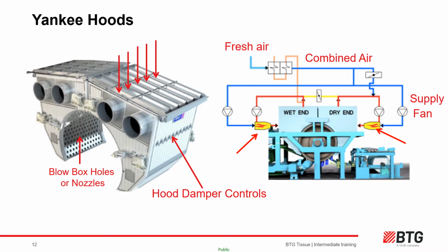The CD hood dampers are usually manually set by the operators, depending on the moisture profile being obtained. Some machines can take feedback from the moisture scanner and automatically control the CD damper positions based on this feedback. The balance between drying through the hoods and drying on the Yankee is referred to as the Yankee hood drying bias. Yankee drying is considered lowest cost, but too hot a Yankee can also lead to sheet blistering, the sheet sticking too fast to the Yankee surface, and also to hard coating. On the other hand, excessive hood drying increases cost and the risk of fires, especially in a dusty environment.